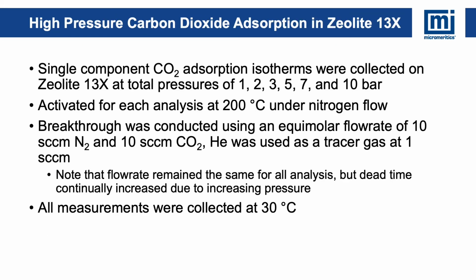Next, I want to talk a little bit about some high-pressure carbon dioxide adsorption in Zeolite 13X. Once again, we collected single-component CO2 adsorption isotherms on Zeolite 13X at total pressures of 1, 2, 3, 5, 7, and 10 bar. We activated the samples for each analysis at 200 degrees Celsius overnight using nitrogen flow, and we did this in between each analysis because, as we saw previously, we were not able to fully reactivate our material unless we exposed it to heat as well.